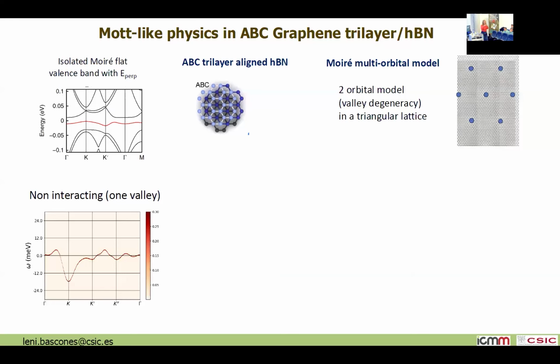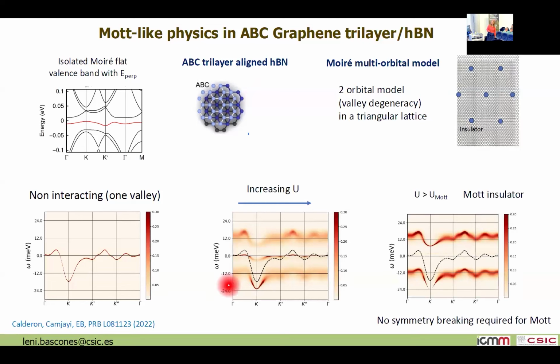So you can see a bit how this happens. For example, to study this type of physics, because it's very much a kind of local physics, you really want to use this type of multi-orbital systems. And so, well, if you have this trilayer that I told you before, and you have this triangular lattice, you can really study what happens when you introduce interactions. And what you see, this is what happens to your band: this is your non-interacting band, you put in the interactions, and what you see is that you are sending a lot of spectral weight to higher energies. Your band is quite destroyed, and these are the Hubbard bands that have been studied a lot in the oxides. And well, if U is quite large, you get an insulator.